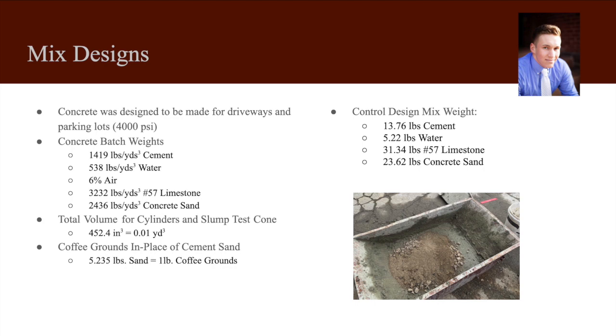And our batch weights are basically the main thing that we can use to find our mix weights. In this case, it mainly helps with the control mix weight. To find the control mix weight, we had to find the total volume of everything the concrete was going to be put into, and this included two cylinders and slump cones that were going to be used to test after the material is mixed together. We were then able to find the control weight, which is shown here, by multiplying our batch weights by the volume in cubic yards. And it just gives us the poundage of each material that is needed.